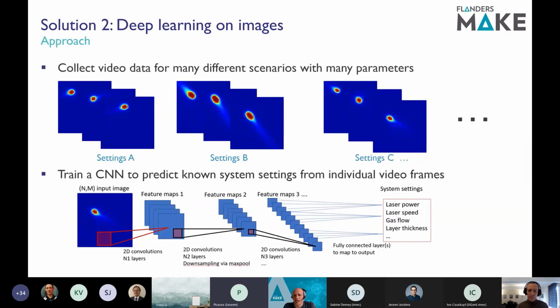So this method works as follows. When there is a new machine or a new material, we execute a kind of calibration print or calibration period. And during this print, we print at different settings. So we have a number of settings, here A, B, C, and many more. We collect some data for each setting. So for each setting, we have a short video stream. And this training data is then fed into a convolutional neural network to find features. So this network will learn how it can derive the system settings from this image by looking at certain patterns or deviations in the image. So we get a mapping from the recorded video frame onto system settings.